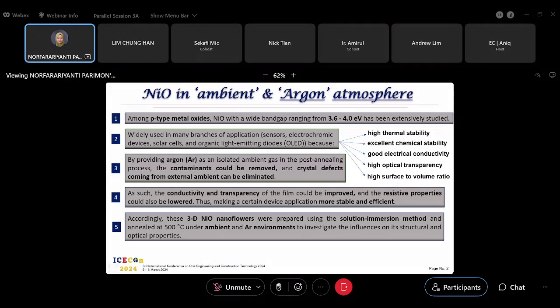So accordingly, for these 3D nickel oxide nanoflowers, we prepared them using the solution immersion method as the main method, and we annealed the sample in ambient and argon environments at 500 degrees C. Then we investigate the influence on its structural and optical properties.